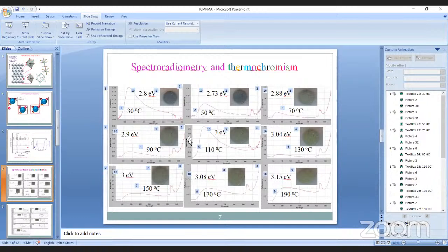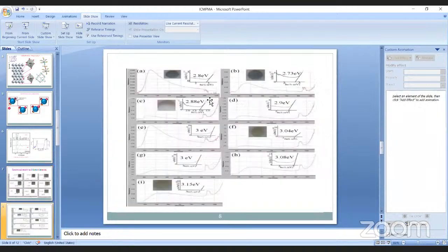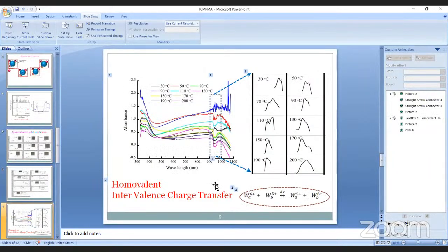Also, there is a change in band gap associated with this color change. This band gap is calculated from the Tauc plot obtained from the sample. The Tauc plot is also shown here in the inset, and from the Tauc plot we can obtain the band gap of this material. The band gap also changes with temperature and varies from 2.8 to 3.15 electron volt. To identify the reason for the change in band gap and for the thermochromism, we consider the absorption spectra of the sample. From the absorption spectra, we get the IVCT band at all temperatures, which corresponds to the intervalence charge transfer taking place in the compound.